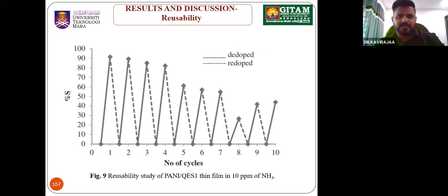For the reusability, we conducted 10 cycles, and it showed that up to 4 cycles, it is kind of stable. But after that, probably because of continuous dedoping and redoping, it denatured, or the reactive parts are blocked away. Next slide.